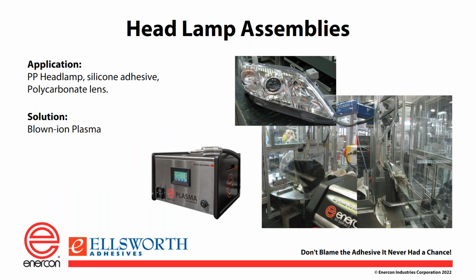Some other applications that we've gotten into in the past: the headlamp is probably the original plasma application. Many older cars, you could see those headlamps fill up with water because they weren't sealed very well, until they started using plasma to treat the polycarbonate lens and the housing, which is polypropylene, and you treat inside that gap. You put the adhesive in there, and once you seal it, now you've got a good solid seal. And you very rarely see the headlamps filled up with water these days because of a poor seal. So this is just an example of what plasma can do to increase that bond strength.